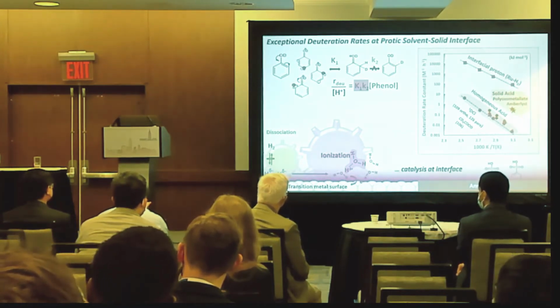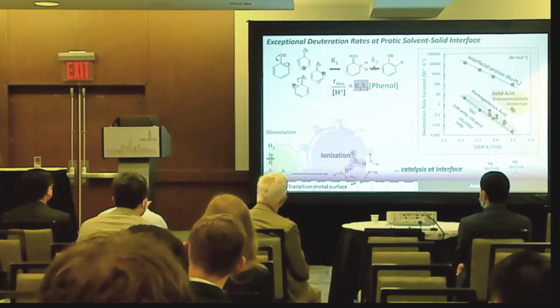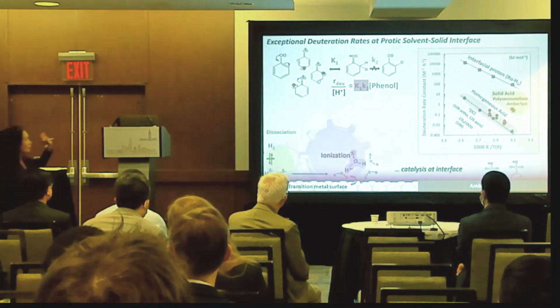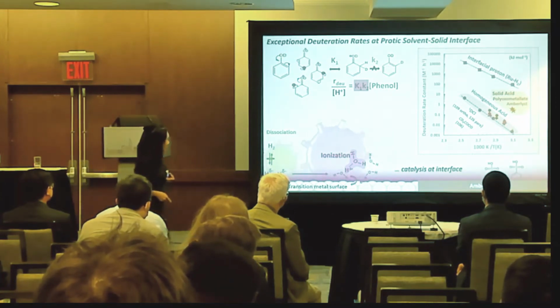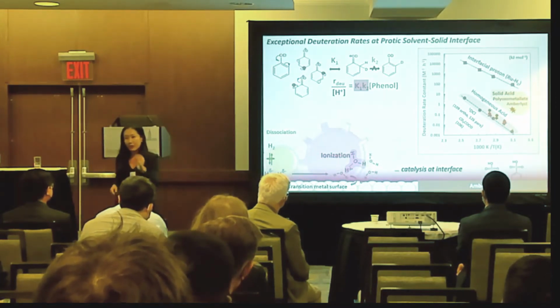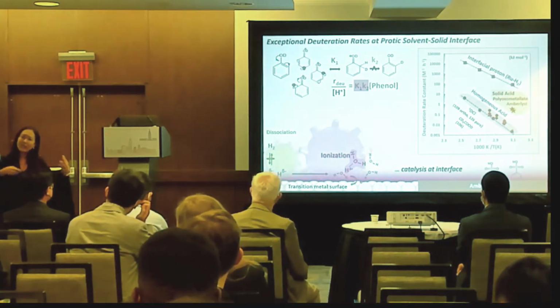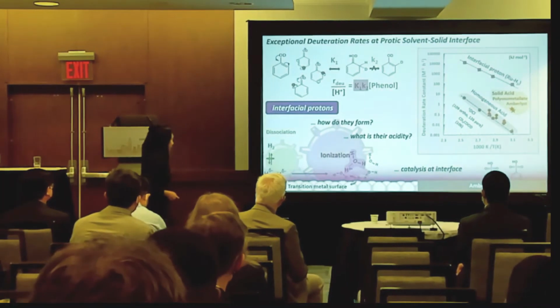We can then compare the second order rate constant for homogeneous versus the heterogeneous surface, and understand that it is not only about the formation of the product, but the fact that the reaction happens at the interface where you have the electrical double layer, where the net charge density polarizes and stabilizes the transition state, so that you get a remarkable turnover rate.